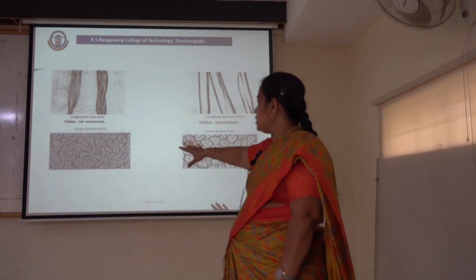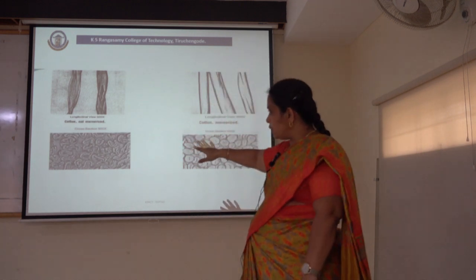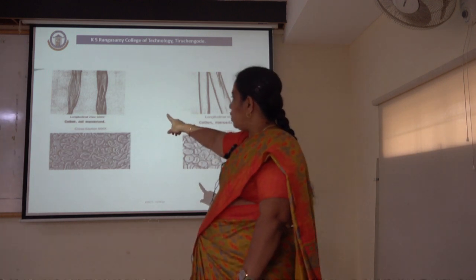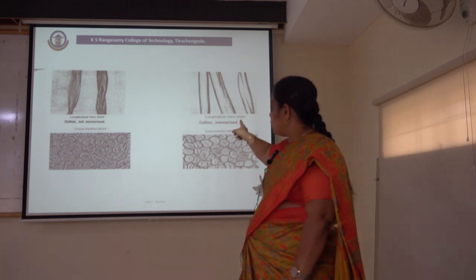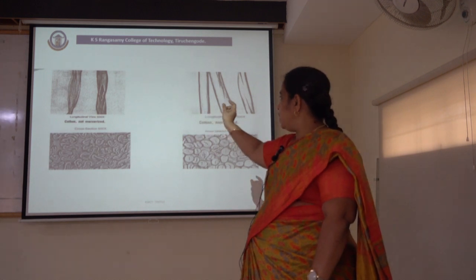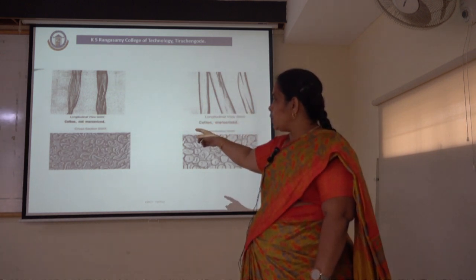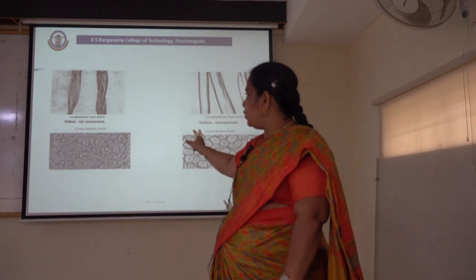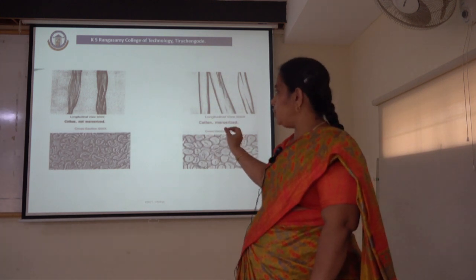This diagram illustrates the longitudinal view and cross-sectional view of an unmercerized cotton material and a mercerized cotton material. Look at the longitudinal view of cotton which has not been mercerized — you see convolutions and a kidney bean shape. In the mercerized cotton, there are no convolutions and it is in the form of a round shape. You can also observe these changes in the cross-sectional view. Only because of these changes occurring during the mercerization process, the luster and dyeability of the textile material is improved to a large extent.